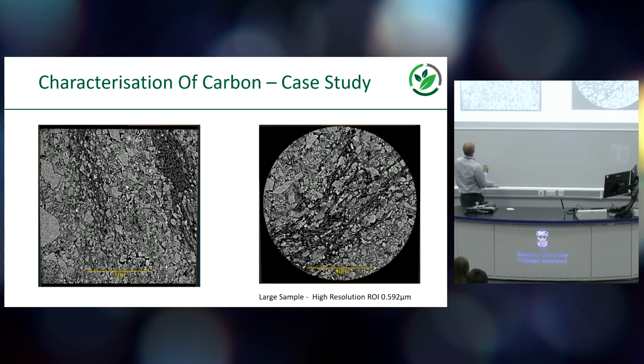Okay. So I want to provide a few examples. So this is a refractory structure that isn't actually strengthened by a combination of phenolic resin and graphite. It's actually phenolic resin and fibres. And we wanted to see, with a high level of industrial relevance, how the distribution of those fibres change through the structure. So one of the things that you can do to try and improve this trade-off that you have between thermal efficiency and strength is to look at different forms of carbon in the structure, which might strengthen it as much for lower carbon additions, and therefore for less of a thermal efficiency penalty.